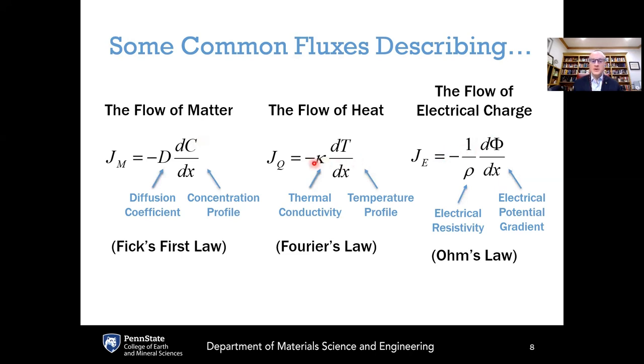And then there's a minus sign out in front because the fluxes that are caused by the thermodynamic driving forces act to lower the thermodynamic driving force. So all three of these equations have the same mathematical form. They are all flux equations, and they were all proposed by these corresponding scientists back in the 19th century, which was several decades before Onsager did his pioneering work on irreversible thermodynamics. So even though irreversible thermodynamics provides a unifying physical basis for all of these flux equations, they were proposed phenomenologically just based on experimental observation by Fick, Fourier, and Ohm well before there was any formal analysis of irreversible thermodynamics.